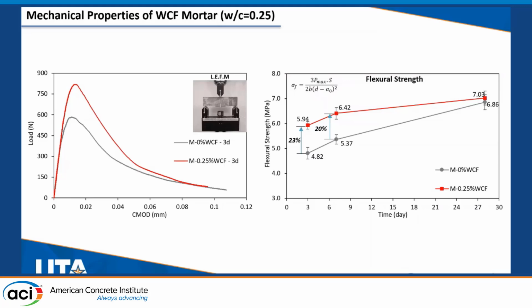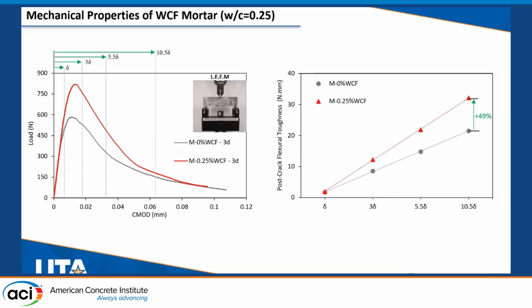In the case of this property, I used linear elastic fracture mechanics to plot the applied load versus the crack mouth opening displacement, and using the peak load of this curve, I plotted the development of flexural strength on the right of the slide. There you can see that the WCF mortar surpasses the plain mortar, especially at the early ages, showcasing at least 20% enhancement. Using the same graph, I calculated the area under these two curves to determine the post-crack flexural toughness at different deflection points. Accordingly, up to 49% enhancement was achieved, which indicates the superior energy absorption capacity of WCF mortars.